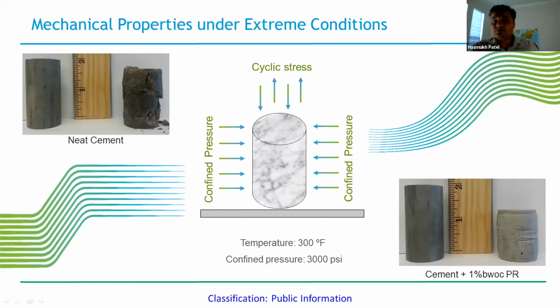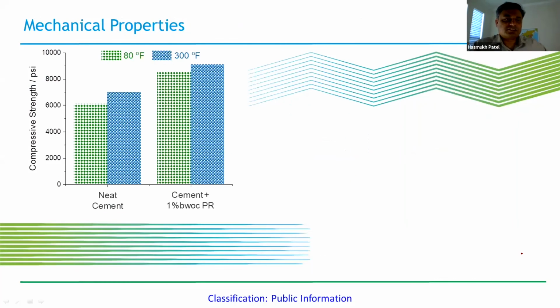So it proves that if we are able to distribute the stresses within the cement uniformly, basically you can preserve your cement samples under such extreme conditions at 150 degrees Celsius and overall pressure of more than 10,000 psi. So let's see the numbers, how the numbers of these mechanical properties look. The neat cement compressive strength is about 6000 psi at room temperature, and at higher temperature about 7,000 psi. With cement with polyrotaxane, we have a little bit higher compressive strength at room temperature as well as 150 degrees Celsius, which is also very unusual.